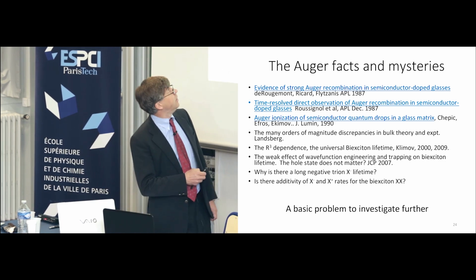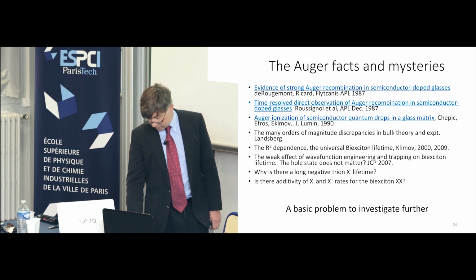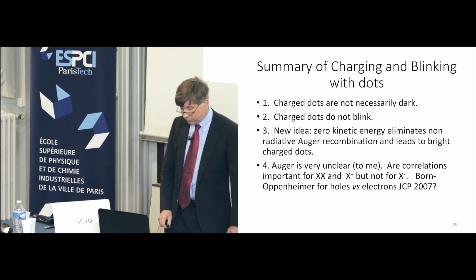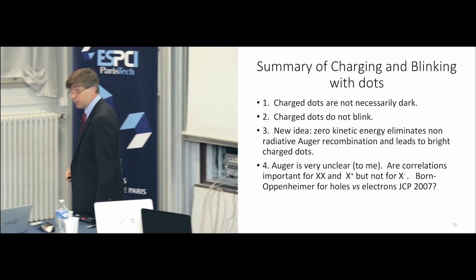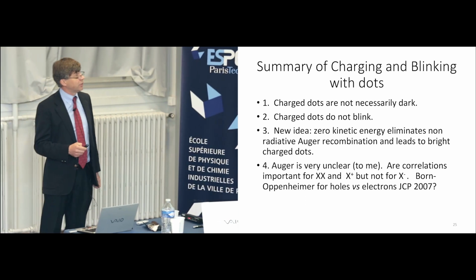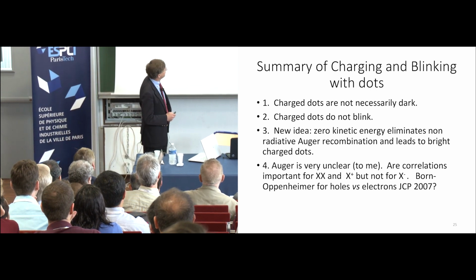There are some funny facts and some interesting mysteries with Auger. So in summary of this part, charged dots are not dark. Charged dots do not blink. We propose a new idea for how we can tune the Auger relaxation of the negative dots. And Auger is very unclear to me.